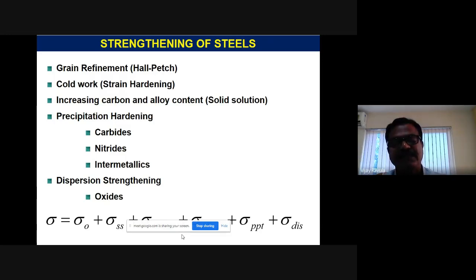And precipitation hardening you can also do by precipitating carbides, nitrides, and then intermetallics like Ni3Al or Ti3Al in the superalloys. That's where the strength comes from for the superalloys. And dispersion strengthening, where you put oxides. So the overall strength is the intrinsic strength of the material plus additional strength from the solid solution, then the strain, then precipitation strengthening, then dispersion strengthening. So basically what we are looking at is oxide dispersion strengthening along with grain refinement. We were able to generate these materials.